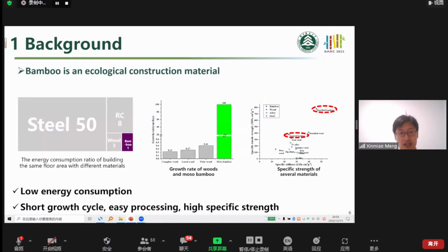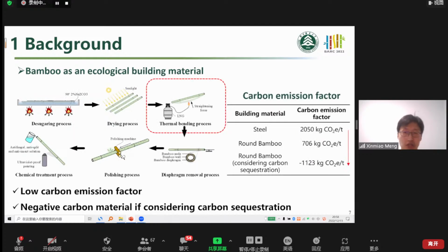Another point is that bamboo is an ecological construction material. It has very low energy consumption, a very short growth cycle, easy processing, and also high strength and light weight. We calculated the carbon emission factor for round bamboo. It was found that the emission factor is very low compared to conventional materials. And if we consider carbon sequestration, it can be a negative carbon material.